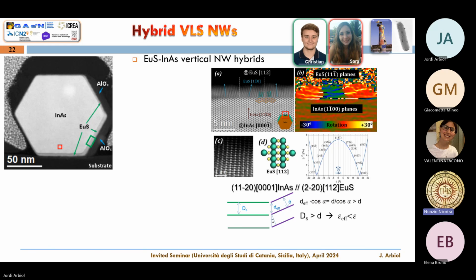But when you are nucleating the europium sulfide, it is nucleated in different points at the same time. And when these crystals grow, they try to adapt to the material beneath, and they do it in the best way they know. So they need to turn or rotate a little bit in order to make all the planes coincident with the ones of the indium arsenide. And this is okay. But then when two of these different boundaries are merging, the problem is that some of them go to the left, some of them go to the right. And these grain boundaries are really messy for the material.